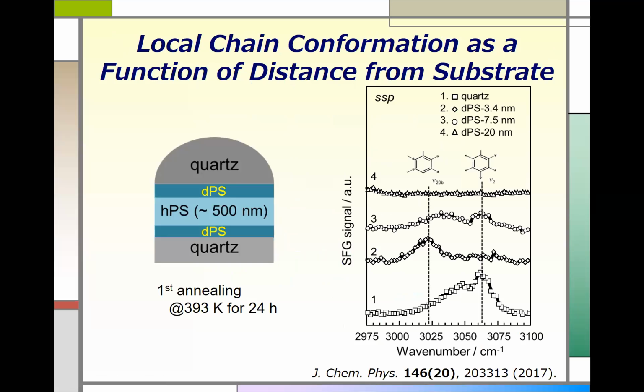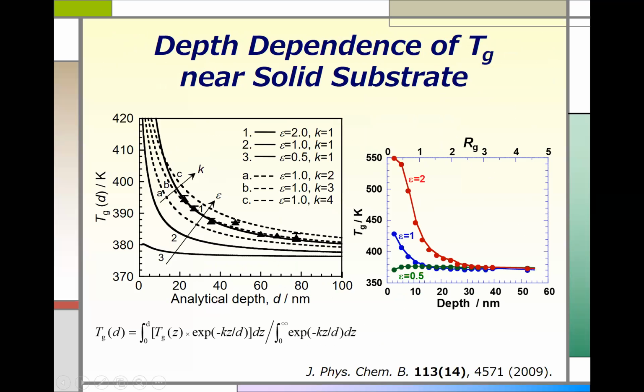So then actually the glass transition temperature of polymers at the solid substrate must be very high. So we measured the glass transition temperature of polystyrene as a function of distance. And actually this is analytical depth. We have used a fluorescence technique, and this data corresponds to the interface between polymer, and this is the polymer side. And going this way, it's the substrate side. Okay, going this way, as I told you, it's bulk. So you see that getting closer to the interface, Tg is going to be very high.